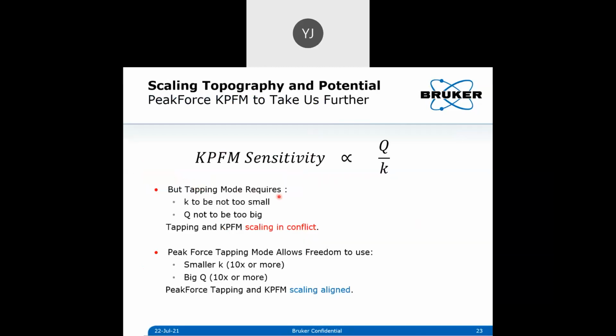KPFM in a traditional sense is done based on the tapping mode, right? So if you're using a tapping mode, anybody who've done it know you will use generally a stiffer cantilever so that you can see the resonance of the cantilever clearly, right? So that means your K is going to be very large. And the quality factor of these cantilevers are generally not too big. So your sensitivity is quite limited by the underlying technique. And because of that, what kind of probes you can choose.